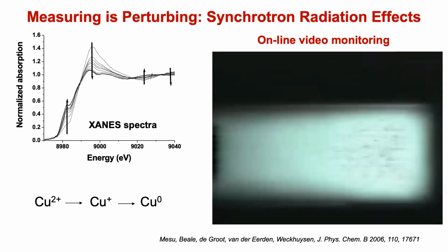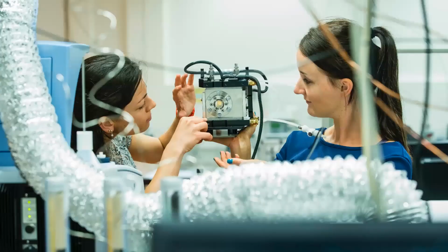So what is happening here? So you have radiolysis, and it leads to splitting of the water. You will get gas formation, hence the bubbles. What you then have is copper is reduced from copper 2 to copper 1 to copper metal. You can analyze with electron microscopy, you'll find copper particles. Was interesting, or is interesting. Maybe if I have time next week, I will show you one in heterogeneous catalysis, because also there, these things can happen. Back to the cell.